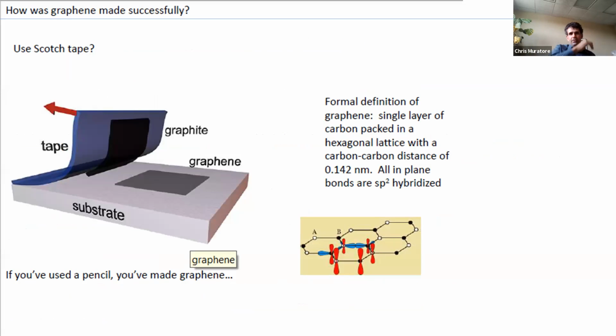But with graphite, there's a similar situation, right? You've got these covalently bound sheets. They're very strong, and they're separated by these van der Waals gaps that make their bonding out of plane very weak. And so it's very easy to tear apart a single crystal of graphite. And if you're very lucky, you'll have some fraction of the material that you've torn apart be only a single layer.